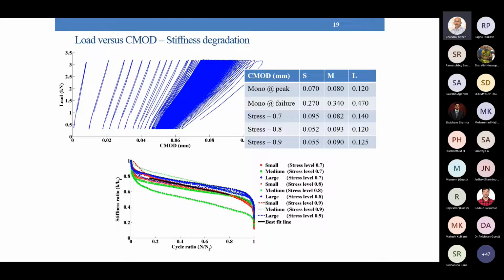Here we see the degradation in the stiffness. We have plotted the load CMOD response obtained from the fatigue experiment at a few cycles, so that we can compute the slope of these. The slope at different cycles is plotted here, which gives us the stiffness. We have plotted the stiffness on the vertical axis and the cycle ratio, normalized with respect to final failure, here. For all the beams, small, medium, large size, at different stress levels, 0.7, 0.8 and 0.9, the behavior is very similar.